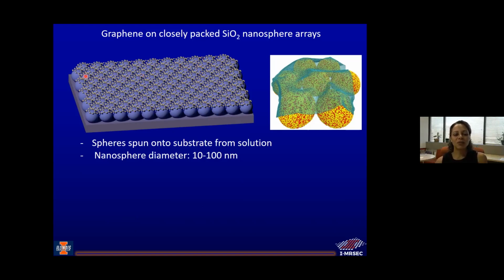So here we've made graphene that's sitting on top of this assembly of nanospheres, where the spheres are spun onto a substrate from a solution, and they're commercially purchased, and they have diameters down to 10 nanometers and that are variable. So you could just buy solutions of these that are really uniform and have diameters from 10 nanometers, 20 nanometers, up to hundreds of nanometers. Okay. And this is a molecular dynamics simulation that our collaborators did, but they show that the graphene will stick to the top of the nanospheres and be strained there in the same way that they were with the pyramids.